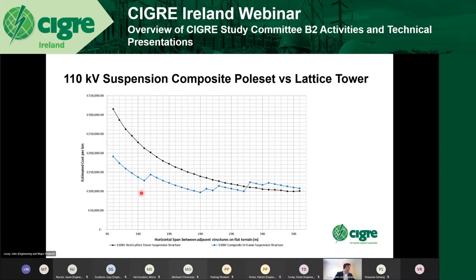Obviously, where it's costing less further down in the spans, you'd probably be comparing it to wood poles. So I'd probably discount the start of the graph, but certainly up around their optimum spans. So for this composite pole example, it's somewhere between 240 and 300, seems to be about their optimum span, and it seems to be costing roughly about the same as a steel lattice tower with an optimum span of about 400.